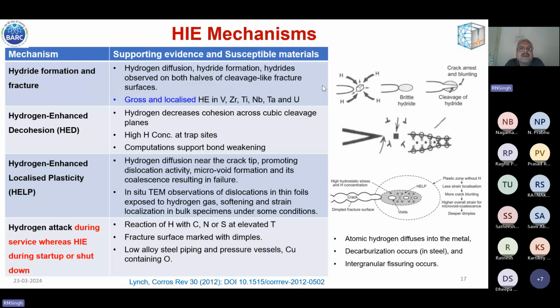Steel, of course, as I mentioned, for austenitic stainless steel, hydrogen embrittlement occurs at very high pressure. But if strain-induced martensite formation is there in some grades of austenitic steel, then the pressure and temperature requirement for embrittlement comes down drastically.